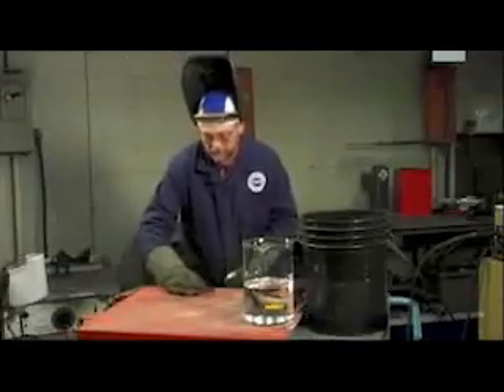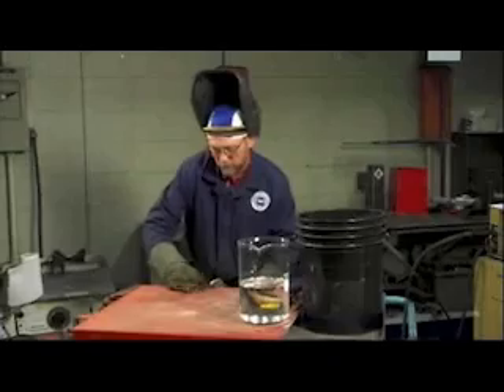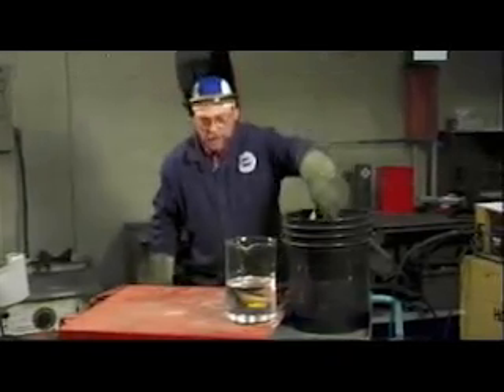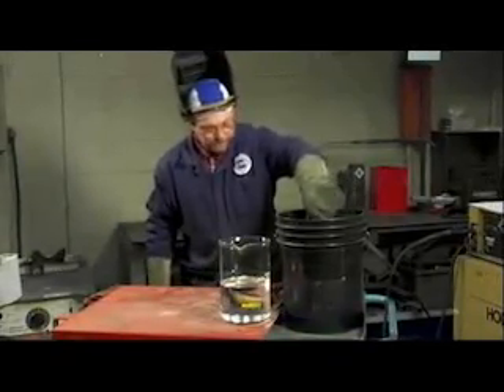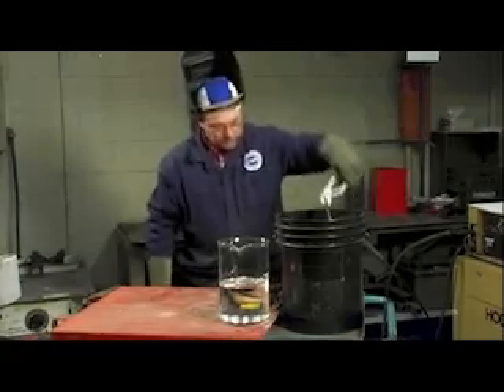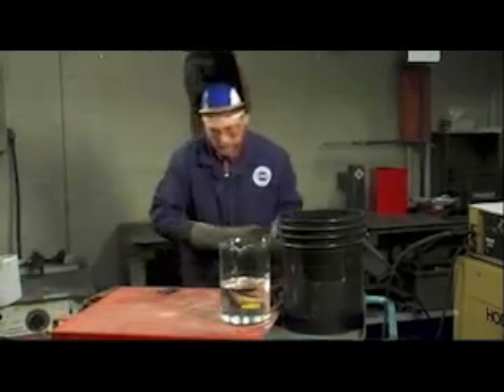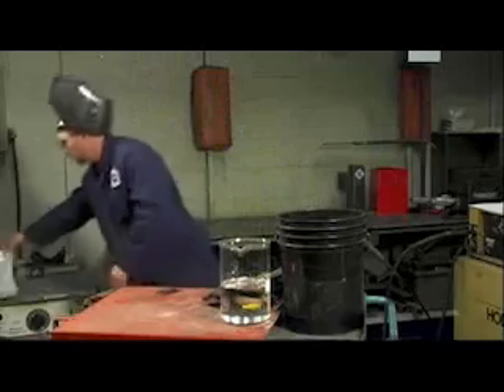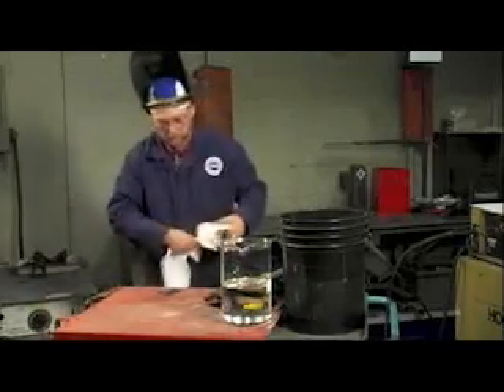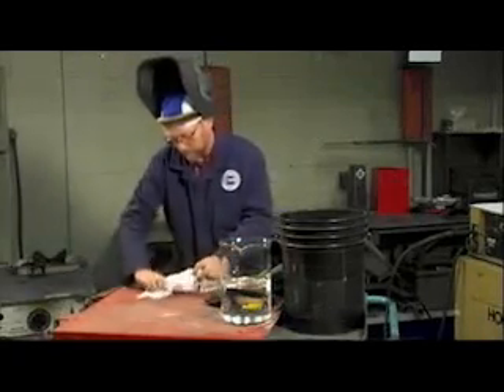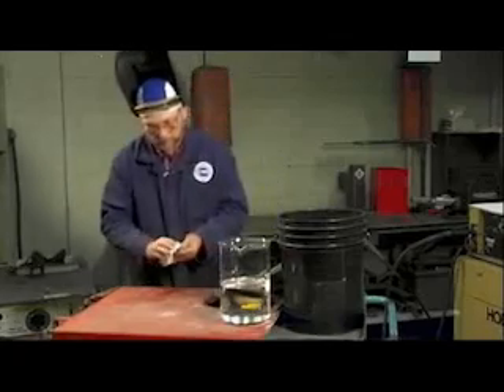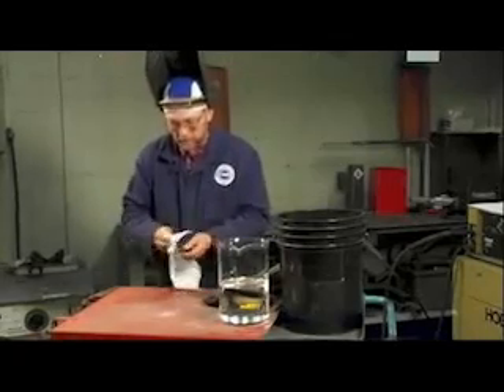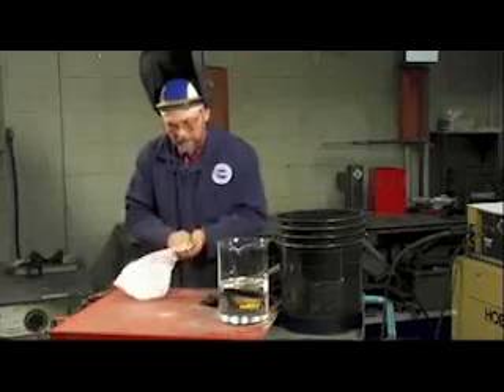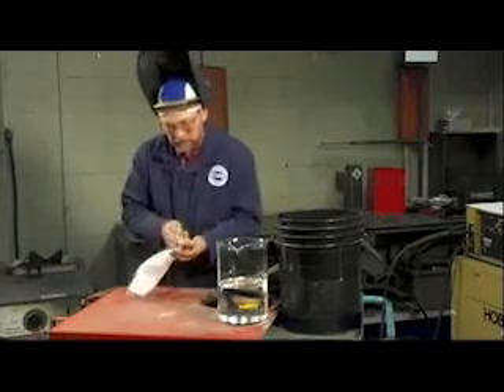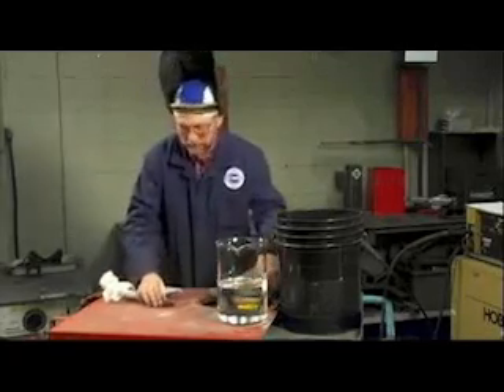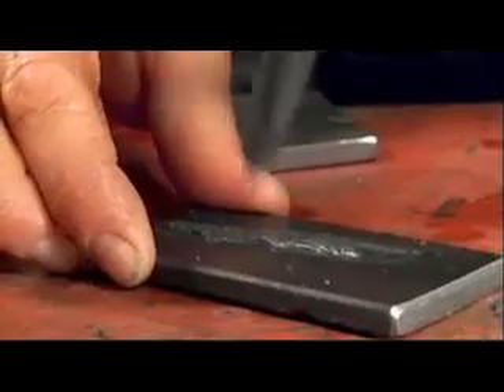Okay, I'm going to take this piece of material and quench it in the cold water to lock the hydrogen into the metal. Just going to dry it off now because the bubbles of hydrogen gas tend to stick to the piece if it's wet. You have to remove the slag as well.